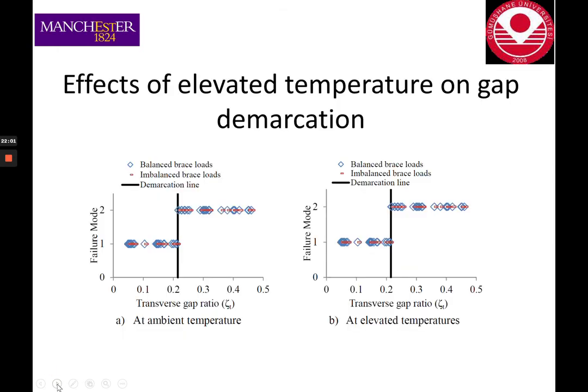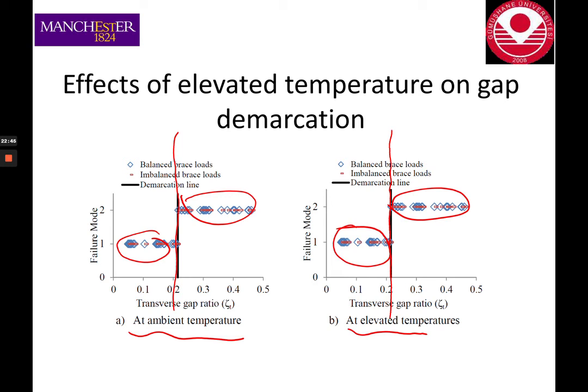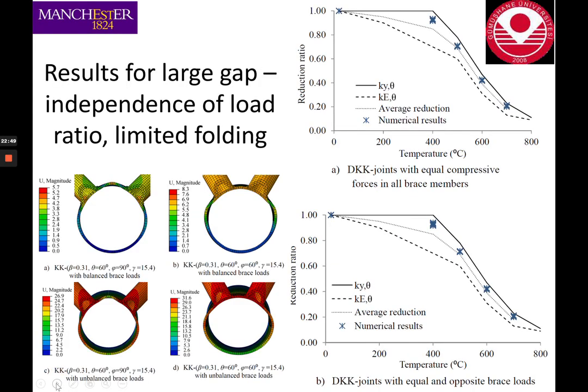Of course, for ambient temperature design, there is a definition of what is a big gap and what is a small gap. We carried out research to see whether the same definition can be applied to high temperatures. These results show that, in fact, yes, we can apply the same definition at ambient temperature to elevated temperatures. This is where the definitions of small gap and big gap, and the failure modes, are the same. As you can see here, the failure modes for small gaps and for large gaps at high temperatures are pretty much the same as at ambient temperature. So that's good. Then for large gaps and small gaps, again, we're trying to find the modification factors for strength. Which modification factor should we apply to the ambient temperature resistance?